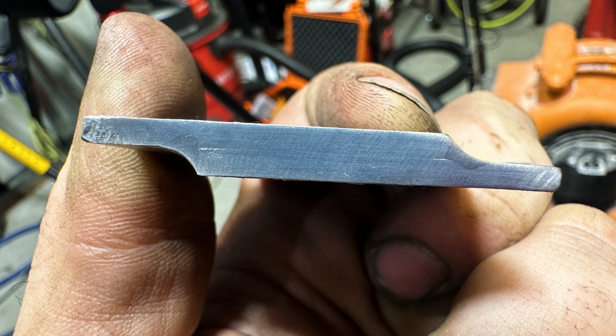Had I moved faster or used less amperage for that weld on the right, there'd probably be no fusion whatsoever, and more or less the weld's actual throat depth, aka what's joining the two pieces of metal together, would have been even thinner than where we're at here, therefore it'd be very weak. And this is exactly what you would expect to see depending on where you're focusing your arc.